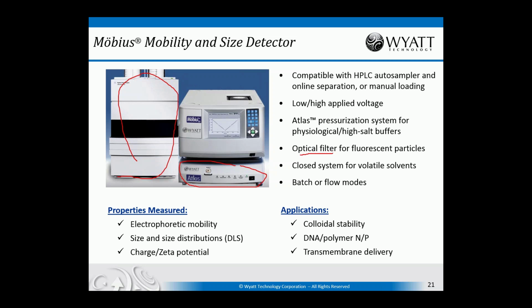Properties measured by this system include the electrophoretic mobility, size and size distributions via the incorporated embedded dynamic light scattering module, and the combination of mobility and DLS allows you to calculate the charge on the particle or its zeta potential. The primary applications are assessments of colloidal stability, so the charge impacts the colloidal stability, but it's also in particular for applications in nanoparticle drug delivery, assessing the NP ratio, that is the ratio, for instance, of DNA to polymer, which will allow you to calculate the net charge, which is really critical for transmembrane delivery if you're thinking about perhaps gene vectors or other applications of these nanoparticles for delivering their payload through a cellular membrane.